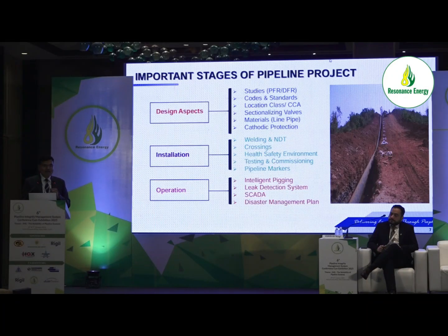And materials like line pipe. In a pipeline, almost 35 to 40% of the cost belongs to line pipe. So line pipe is a very critical item for any pipeline system, for the integrity of the pipeline system. And the last one is cathodic protection, because the pipeline is coated, but coating has pores, as any plastic material has pores. Through those pores current can leak, or there can be some damage in the coating, so we provide a cathodic protection system to protect the pipeline from external corrosion.